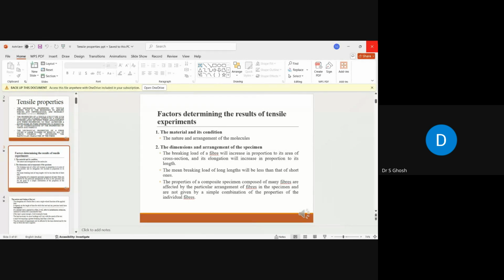Textile material is very susceptible to the condition in which you are doing testing. That's why if the condition changes, your result will change. That's why we always suggest that whenever you would like to do testing of textile material, go for standard testing conditions and expose your materials 24 hours before the testing, so that any problem with the materials, or the history of the material, will be normalized. If any prehistory is there, it should be normalized.